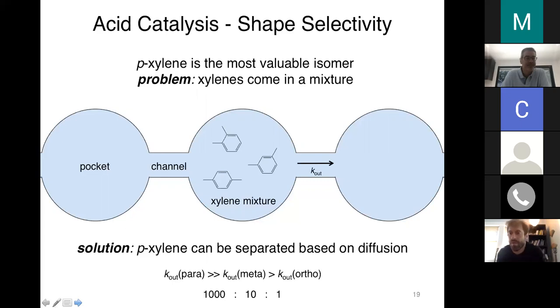So one thing you can do is a chromatographic style separation of these isomers using a zeolite. The idea here is that paraxylene is the least sterically demanding of all of the xylenes. So if you flow this mixture through a zeolite lattice, the para isomer is going to move through the lattice more rapidly because it can get through the constricted spaces more rapidly. People have quantified this, and they find that the rate of diffusion for the para isomer is typically up to 1,000-fold more rapid than that of the ortho isomer. So you can do a pretty efficient chromatographic style separation of these isomers using a reactor bed packed with zeolites.